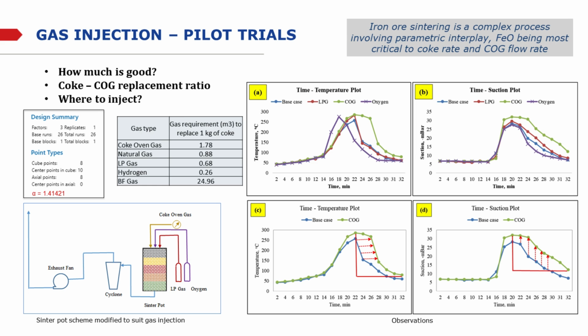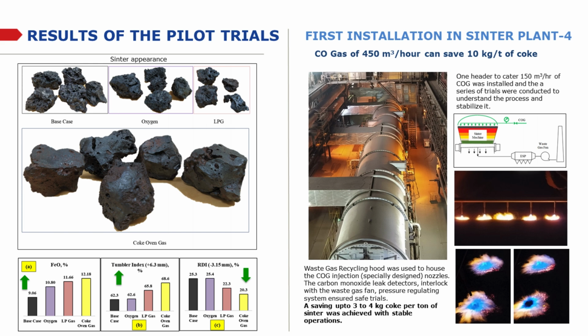Oxygen, which can improve the combustion efficiency of coke, and liquefied petroleum gas (LPG) as an alternate gaseous fuel were injected to see their effects. The coke oven gas has about 57% hydrogen, a carbon neutral source of heat and reductant of the iron ore. When injected, COG outperformed LPG. Hydrogen in the COG enhanced FeO formation. Superior mineralogical phase assemblages were noticed, which resulted in enhanced properties of the sinter.